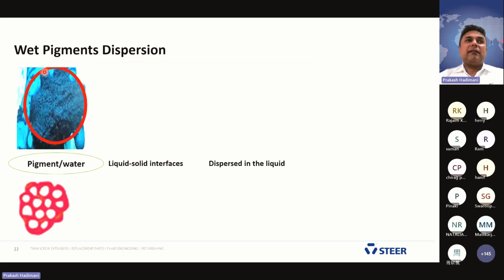Wet pigment dispersion. Here, this is the wet pigment. It combines polymer powder and the pigment, and 60 to 70% water in this mass. Currently, yes, if you take this, it's difficult to feed. It's a lump. And how to feed it? Okay, that's a big challenge. To overcome this challenge for wet pigment, Steer has introduced a new technology, a feeding mechanism to feed the wet pigment into the extruder. When you take this wet pigment from the manufacturer, it combines pigments and water.